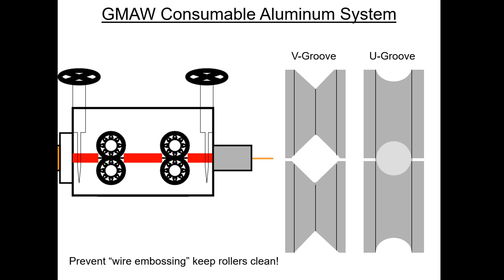If your drive rolls get dirty, they start to push dirt and grime and anything else that might be around back into the wire. When they push it back into the wire, they're actually creating a rough surface. And that rough surface has to eventually go through the contact tip and become electrified. And when it becomes electrified, then we get our weld. But if that surface is terrible, if it's been chewed up by our drive rolls, whether they're dirty or just damaged, it has to be addressed, because it will bring you to a stop and you'll be struggling all night trying to figure out why this machine won't work.